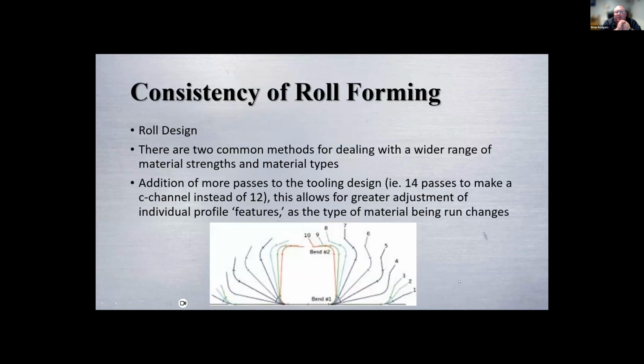So when we are talking about the consistency, we really look at the roll design. And when we're looking at the roll design, we're trying to make sure that we're holding that consistency and we're eliminating things like flare. What flare is at the end of a part when it's cut off, because of the forming process, it has residual stresses. So when you release it, it wants to spring open a little bit on the exit side of the part, or it wants to toe in on the entrance side. And the reason for that is, as it's going through the tooling, it's being knocked in. So that's where you get the toe in on the leading. And on the exit, it's allowed to release. So it wants to flare out.